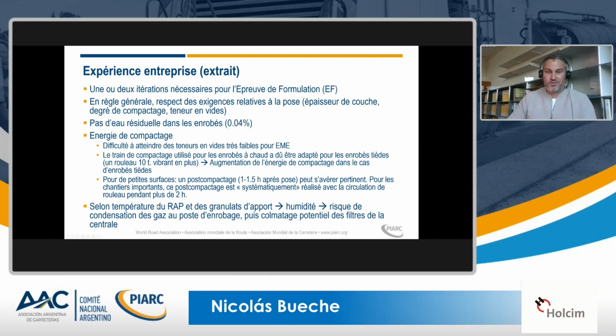The last point is also a bit tricky, maybe it's more related to the Swiss case. We have a lot of batch plants, and so if we produce warm mix in the batch plant with a high RAP content, we have some, let's say, risk of clogging in the asphalt plant, which might create some problems. So we always have to be careful with the humidity aspect also in the asphalt plants.